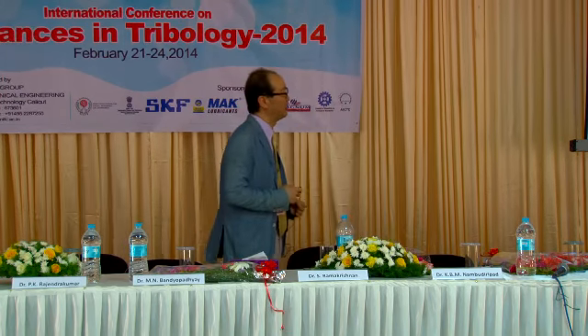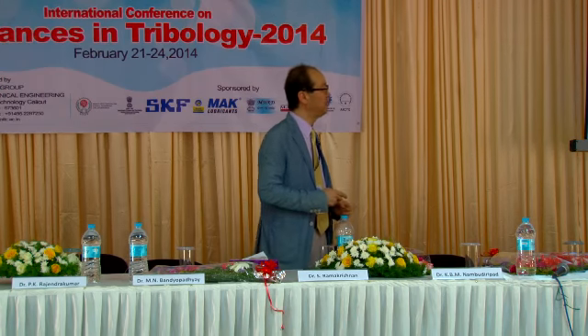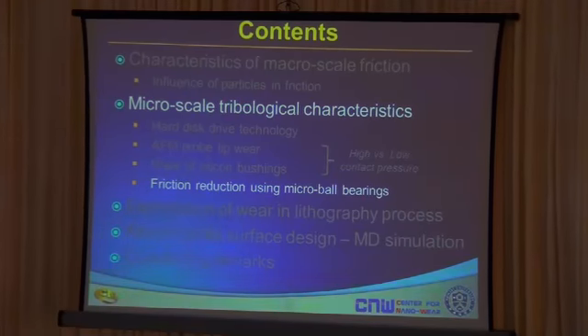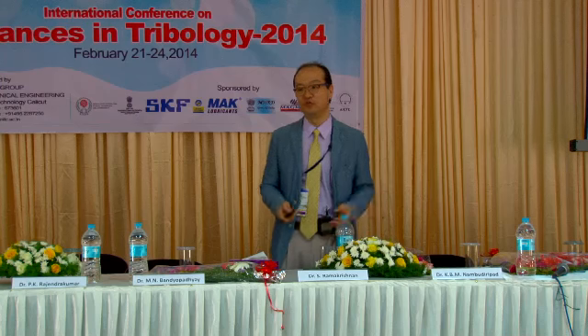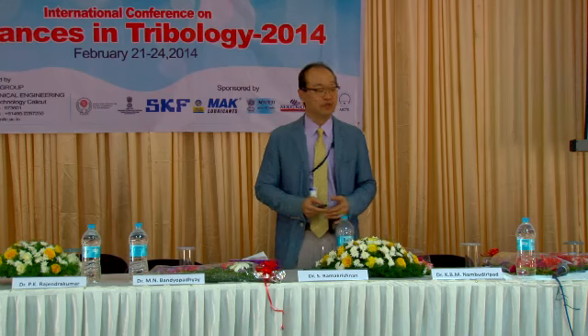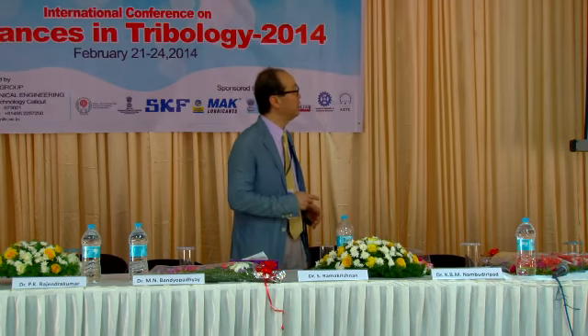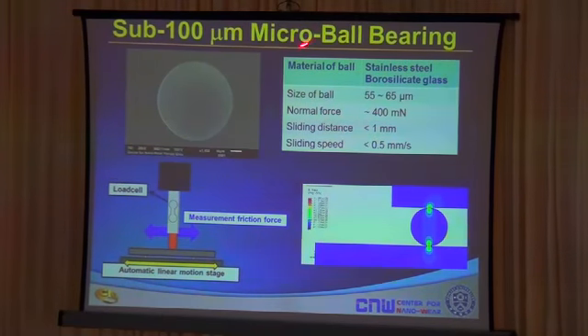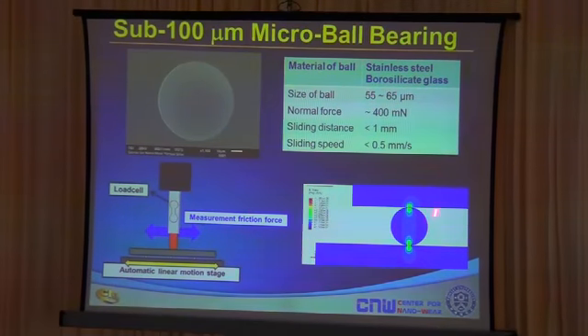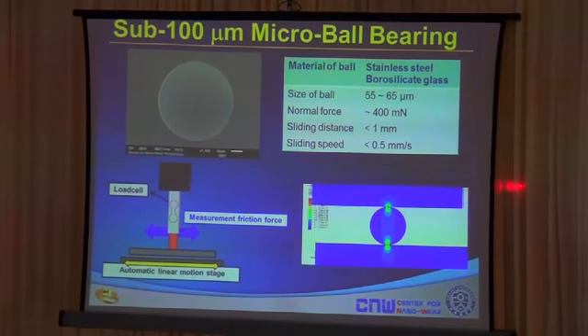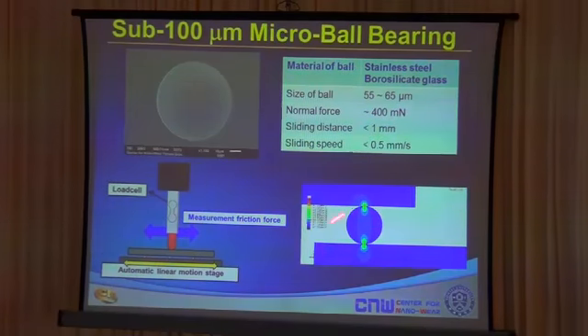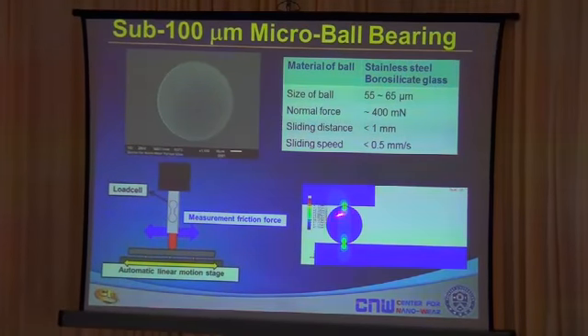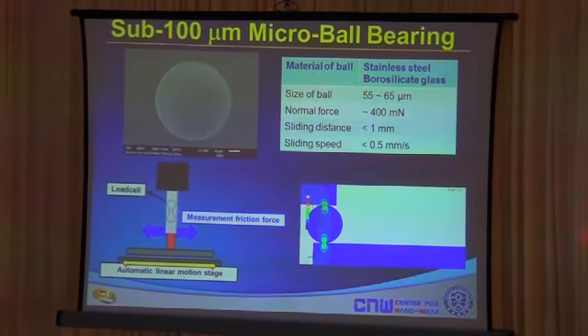Now I'd like to look into the way of reducing friction using micro ball bearings. As we all know, we use bearings extensively in all machines. So in the case of micro components, why not try to use micro ball bearings as well? So what we did was we tried to apply sub-100 micrometer size micro ball bearings, and what we do is we place it between two flat surfaces and we drive the top surface and see the rolling friction with this micro ball bearing between the two flat surfaces.